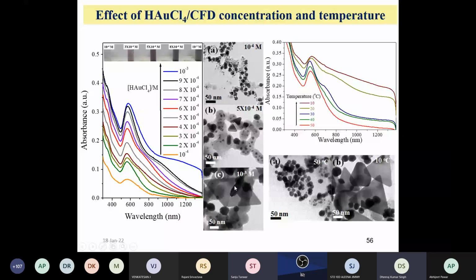You can see here, the red one showing the 50 degree, means larger temperature. At the larger temperature, you can see that this anisotropic NIR region peak, at more than 1000 nanometer, is not observed. It means that at higher temperature, nucleation is much faster and you will find more spherical particles. But when we decrease the temperature from 50 to 10 degree, means the upper part, this brown UV visible spectrum, you can see that in the NIR region, a hump absorption peak is coming here.